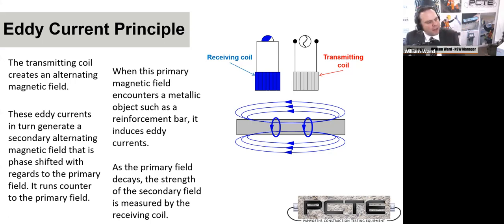The other thing is, if you look in the manuals of the Profometer or Profoscope cover meters, there's actually a wonderful diagram that shows you the additional uncertainty you would add to your measurements if you go from, say, a 16 mm bar. Let's say you enter a 16 mm bar and you're unsure if you've got a 25 or a 12, you could actually work out and include in your reporting work the additional imprecision your lack of knowledge gives. Now, ideally, you can break down and have a look at a reinforcing steel bar. One thing you should not do is use the estimate functions to try and enter it. It's better to either use knowledge of how the structure is constructed to choose reinforcing steel sizes when you don't know it, or to physically investigate the size of the reinforcing steel.